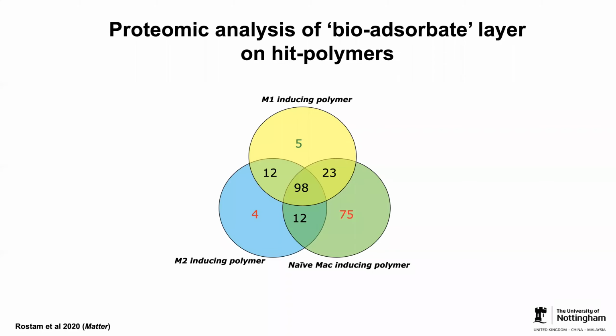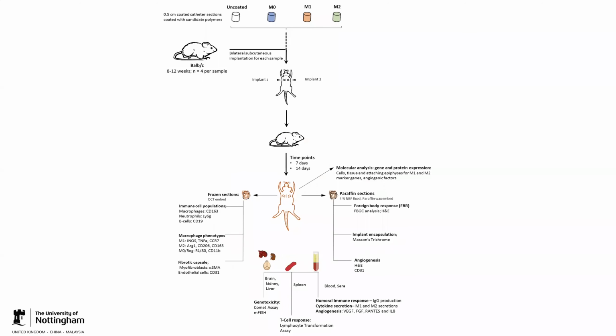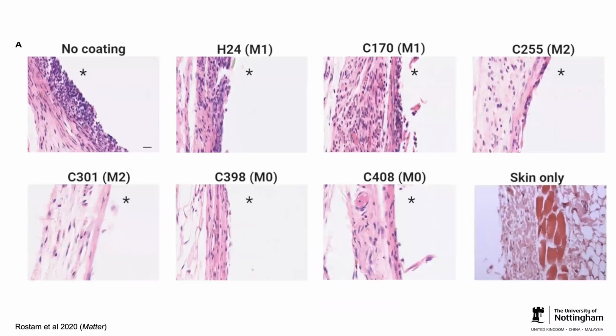Of course, we still need a lot more to do in terms of understanding the mechanism, but that doesn't stop us from exploring the translational value of these by using them in vivo, and that's exactly what we have done. So we've used an in vivo subcutaneous foreign body model by coating pieces of medical grade catheters and then subcutaneously implanting them in an animal model, following it up to 4 weeks, and then characterizing the immune response locally, and then the impact on fibrotic capsule formation and cell infiltration, and some other readouts that tell us a bit more about how these polymers could influence cellular responses upon implantation.